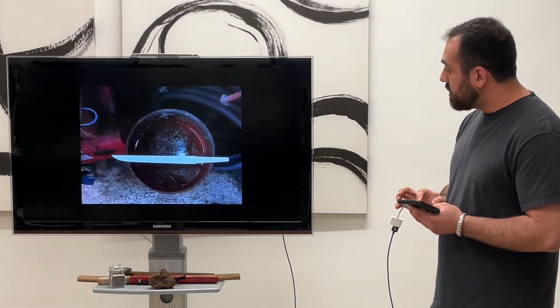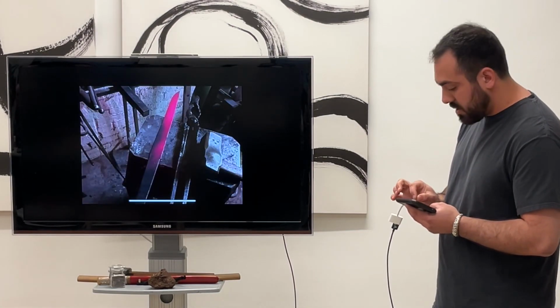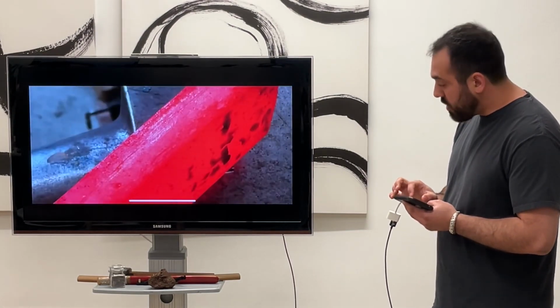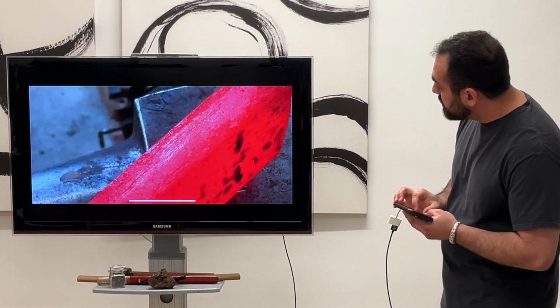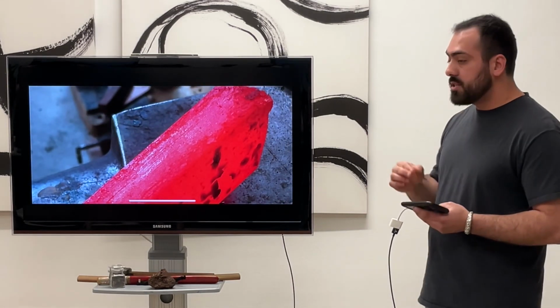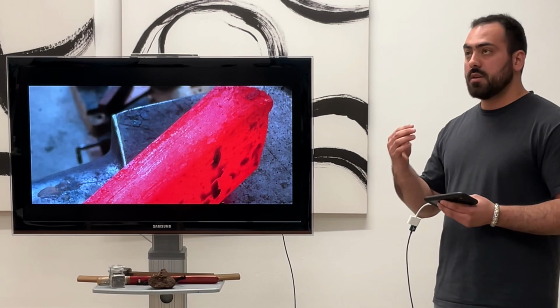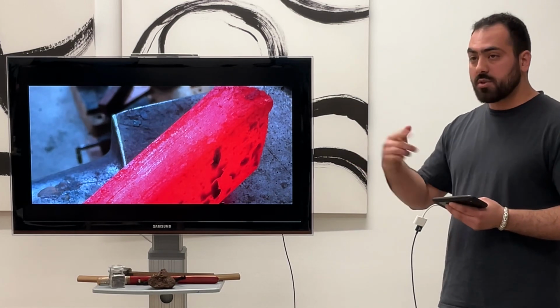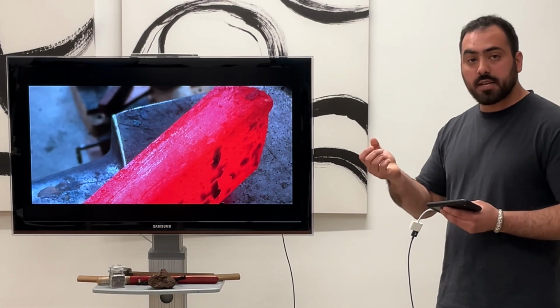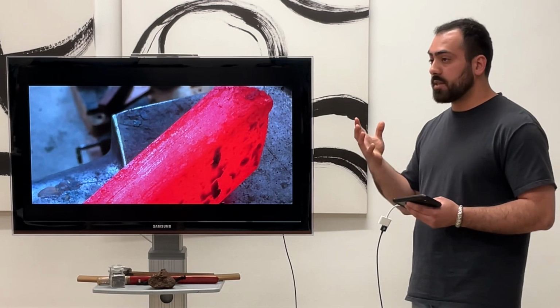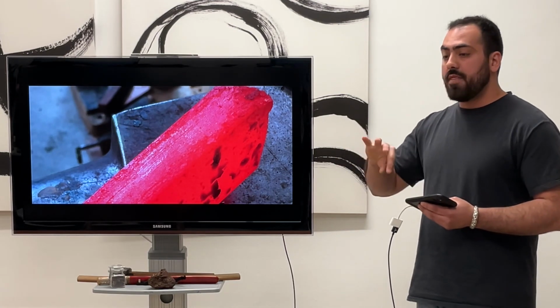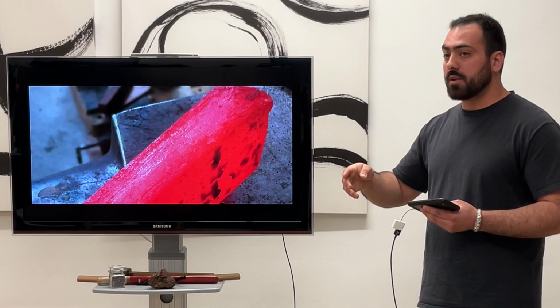So you can see some of the striations here from the different layers as I'm folding. I generally do 4 or 5 folds in the same direction to start getting rid of the pockets, the inclusions, the other crap that's stuck inside still, and then I'll start to switch directions in my folding.